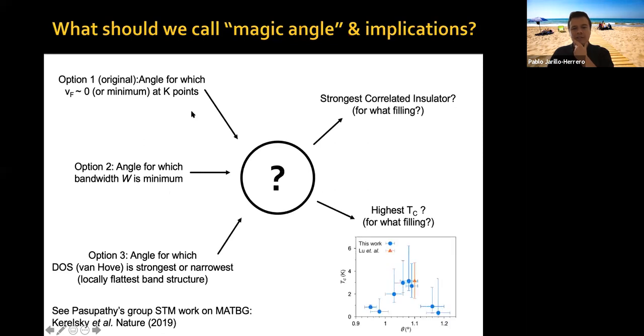The problem is that we don't know yet how any of these three definitions relates to the magic part, okay? Is the most magic angle when experimentally the strongest correlated insulator occurs? And for what fillings? Because the behavior is pretty particle-hole asymmetric around charge neutrality. So electron filling factors behave quite differently from hole filling factors. Or should we call magic angle the angle for which we have the highest TC? And again, for what filling? Because there are multiple superconducting domes, okay? So all of this, the connection between theory and experiment, despite a tremendous amount of very interesting theoretical work, is not yet settled, I would say, at all, okay?